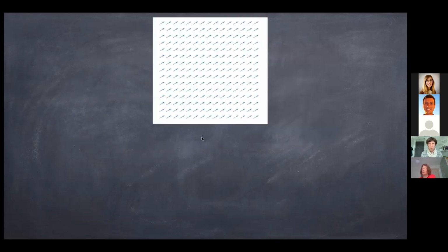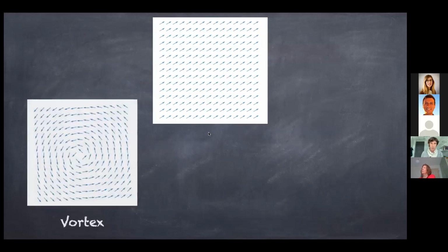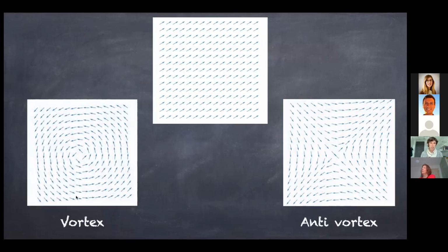So the lowest possible energy state is what's called a magnetized state, where all the spins are pointing in the same direction. They're all lined up with each other, so that gives us the lowest possible energy. But then you can also have these interesting configurations like vortices and anti-vortices, where there's a bit of a problem here, a singularity, a high energy contribution in the middle, and where the spins wrap around. And then everywhere far away from that, they try to line up as best they can, and they get pretty close to lining up.